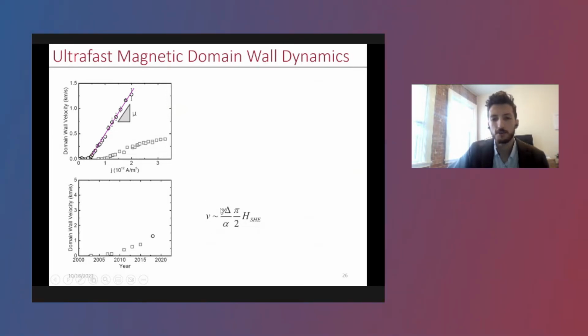materials parameters. There's the gyromagnetic ratio and the domain wall width, which are actually pretty hard to engineer, or they scale in the wrong direction. So for example, the larger the domain wall width, the larger the mobility, which is not scaling correctly. However, in the denominator of this equation, we have the Gilbert damping, which is actually quite easy to engineer depending on the type of material you have.